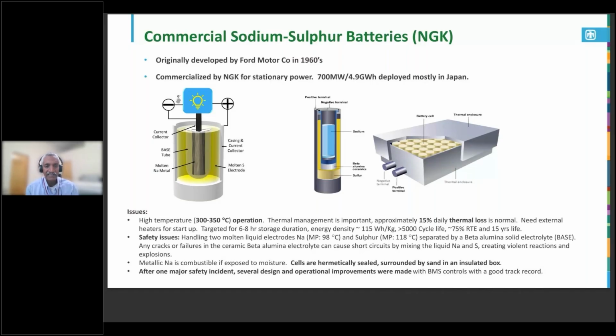It can maintain it. These are targeted for 6 to 8 hours of storage. Energy density is about 115 watt hours per kilogram. They've shown more than 5,000 cycle life. Round trip efficiency is about 75% and 15-year life. These batteries are commercial actually.